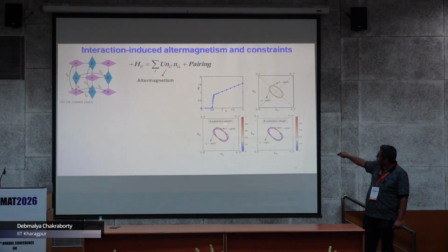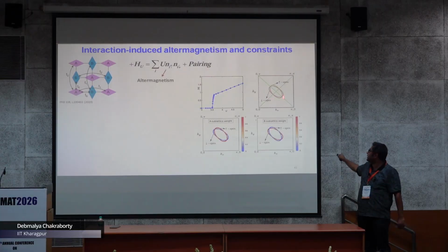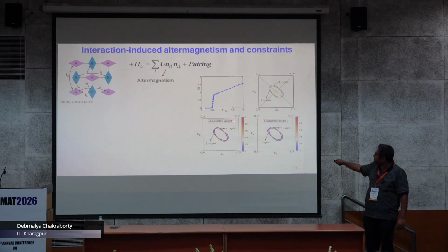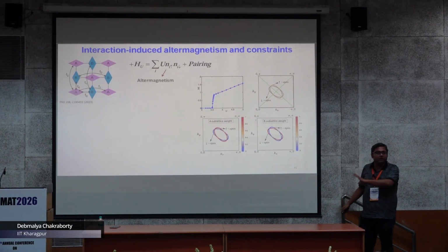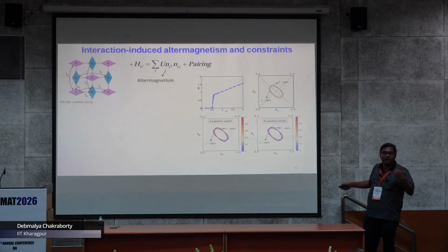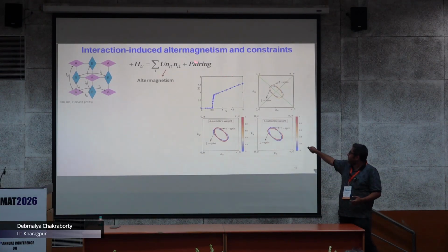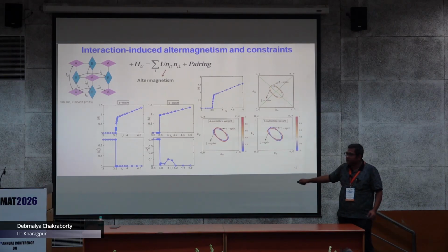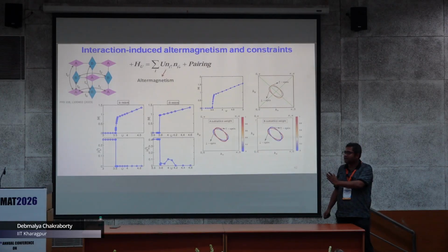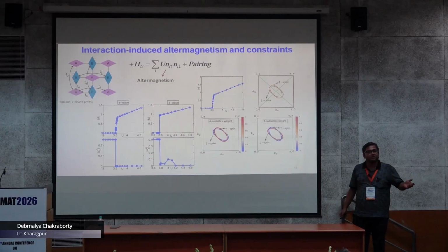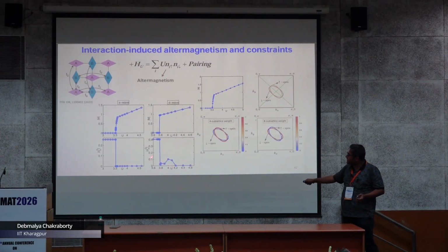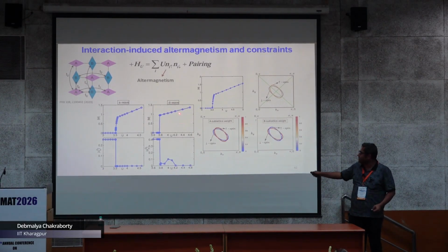And if you look at the sublattice contribution of these individual spins, you will see that this up spin is actually fully A polarized. You can actually calculate it. You can also calculate the B sublattice weight, and it will be polarized for the down spin. And now if we add pairing, we can see that s-wave goes away as soon as we have M coming up from this Hubbard repulsion. As soon as M comes up, s-wave becomes 0, there is no possibility. But if we allow for d-wave, we will see that there is a finite momentum pairing coming up near the transition.